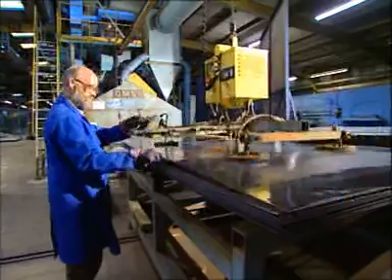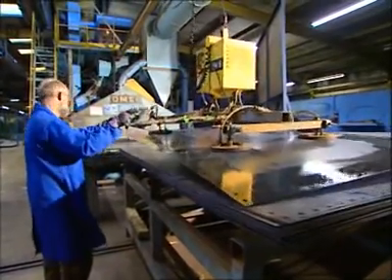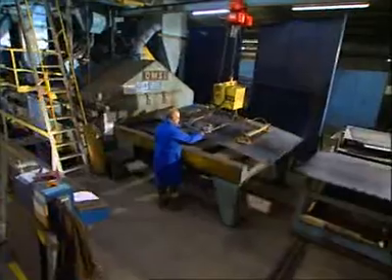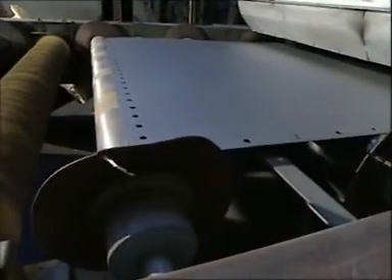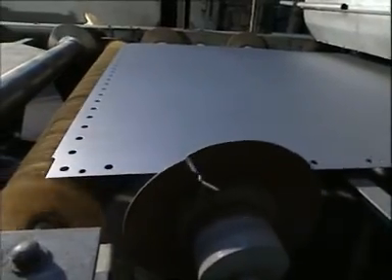Before the sheet can be coated, it must be cleaned, starting with one of the most important pieces of equipment in the whole process: the grit blaster. This machine fires some 3.5 tons of angular steel grit per minute to produce a high-quality roughened key surface. There is a second blast machine and a grit blast chamber for fabricated components.